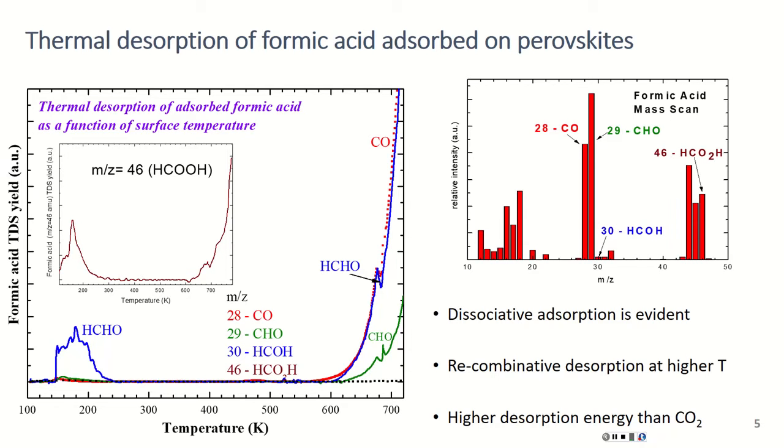Okay, so there might be a molecular precursor for the dissociation, I guess, because you see a molecular peak, right? But I guess the dissociation must happen before 200 Kelvin or so, and those fragments adsorb on the surface in the submonolayer range. Below the monolayer range, the binding energy is higher, so it needs a higher temperature for desorption.